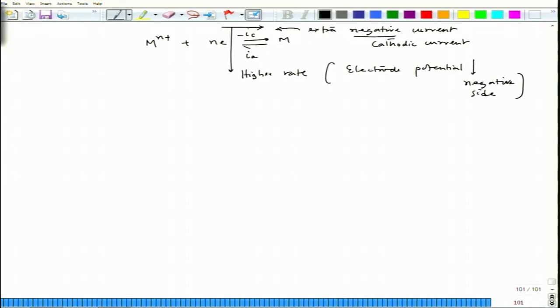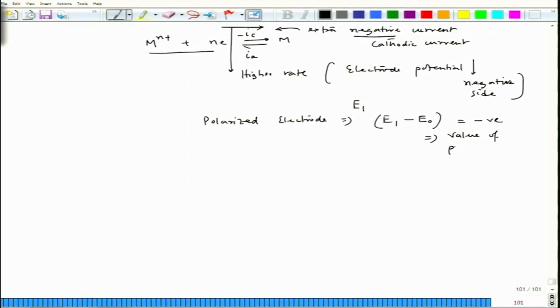So, why negative side? Because when it switches to the negative side, this metal surface is becoming more and more negative, and that is why the supply of electron to this reduction process would become easy. So, then the potential becomes, let us say, E 1. Now, this is called polarized electrode. And that time the value of the polarization would be E 1 minus E 0, because now we have switched from E 0 to E 1. This is also negative, since the potential goes to the negative side, and this is the value of polarization. Or we call it eta C. C is nothing but the cathodic.